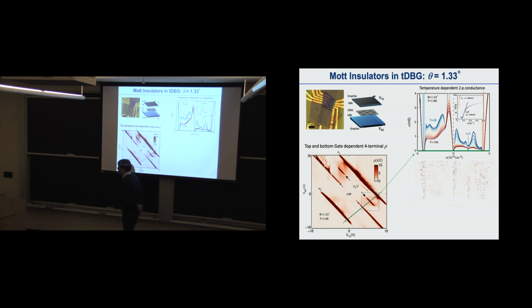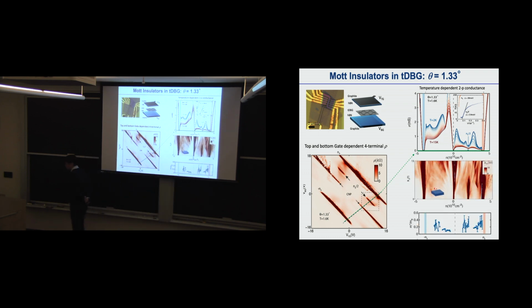By applying a magnetic field and looking at the quantum oscillations, we get the mass, and all of this state we're creating has a reasonably high mass, which also supports that this is really a correlated state with a reasonably high mass compared to the single particle gap.